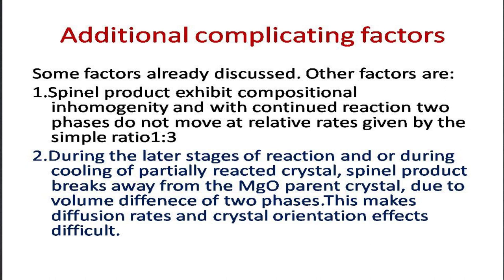The two phases may not move at the relative rate, as we have seen in the ratio of 1:3. Now I must mention here that 1:3 is the ratio that you obtain in the reaction, the layer formation. In actual experience, this has been found to be 1:2.7, which is very close to 1:3. So therefore, all our efforts confirm that we are proceeding in the right direction, and the ratios that we are using, they are correct.